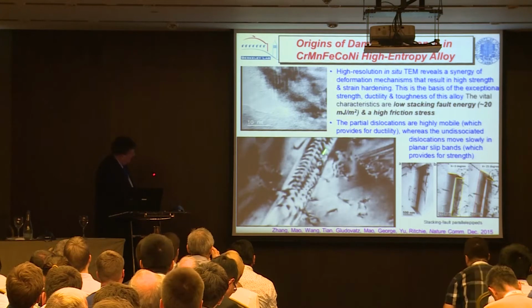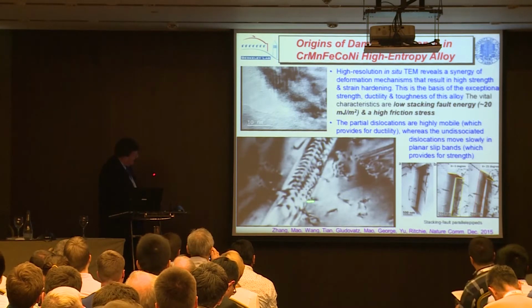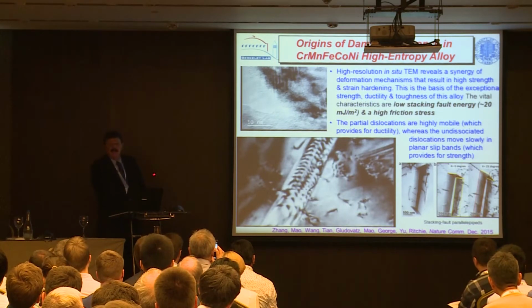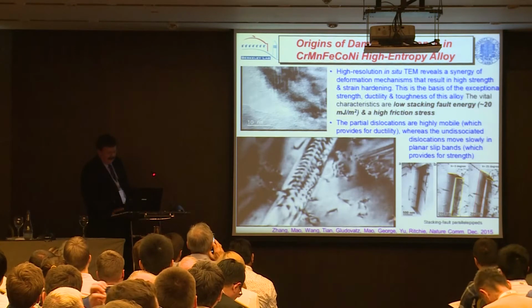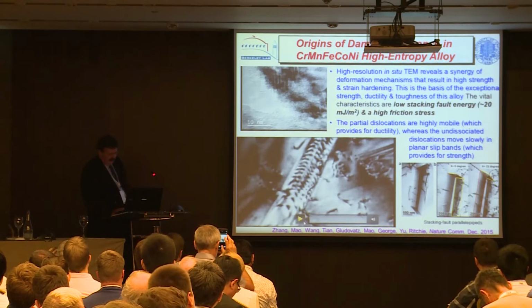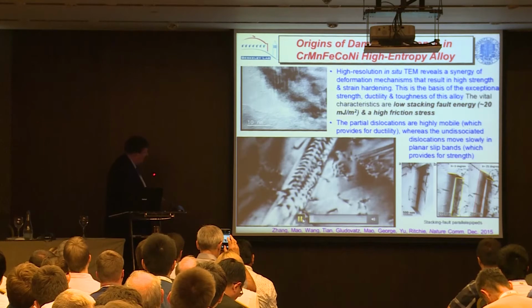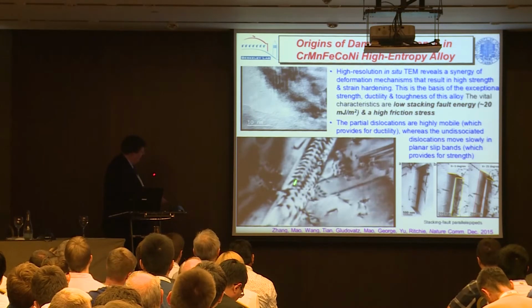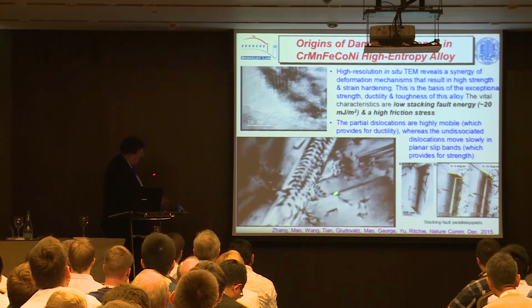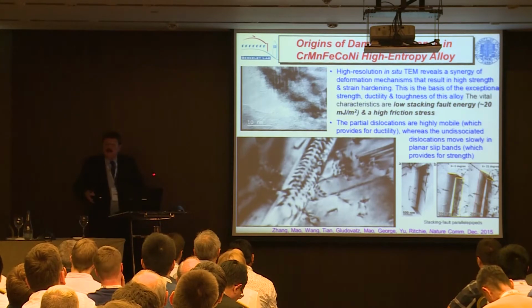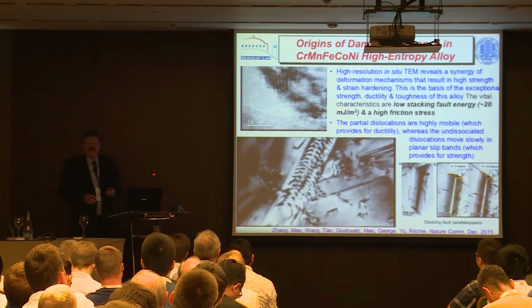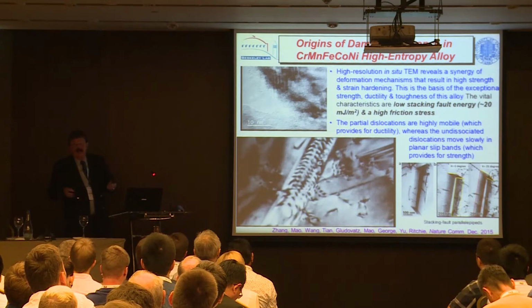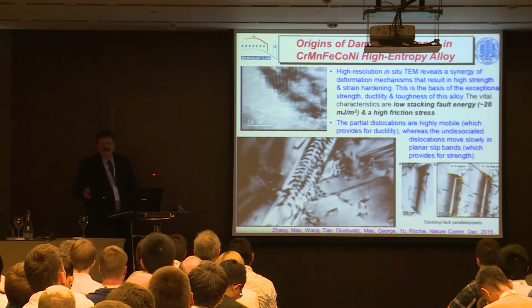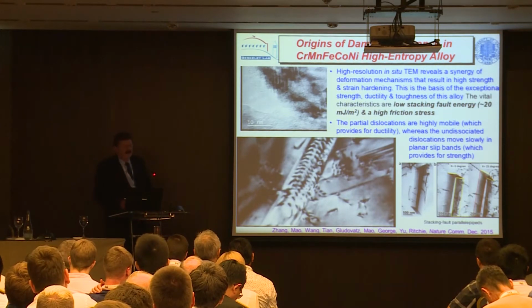These perfect dislocations are moving very slowly, but you'll see a partial dislocation move in like greased lightning next to it. So again, you can see the slow movement, and there's the partial coming in very, very rapidly. So we have a duality of mechanisms. We have a ponderous movement of the undissociated dislocations that provide strength. We get the rapid motion of the partials that give us ductility.